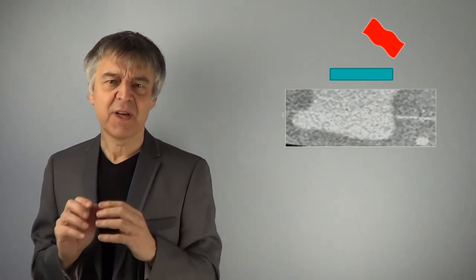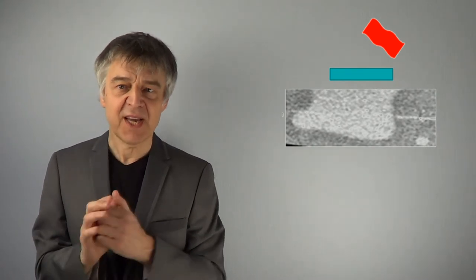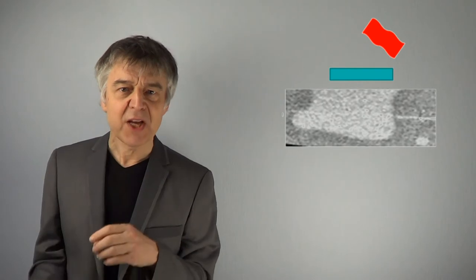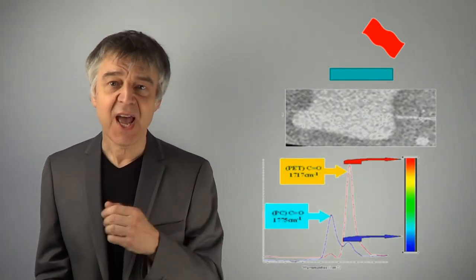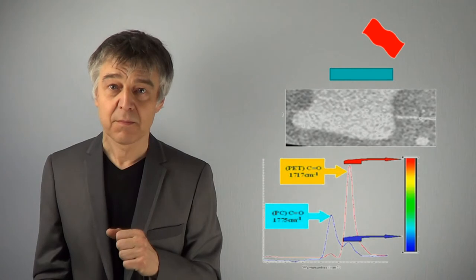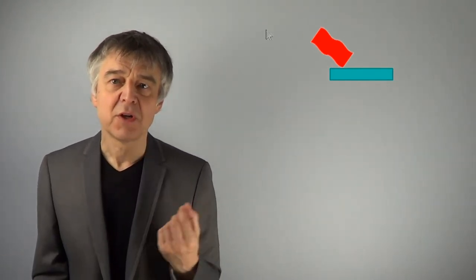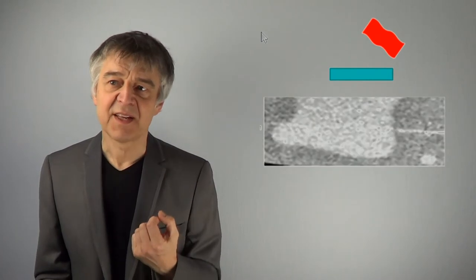By means of infrared spectroscopy in ATR mode, we can distinguish the vibration bands of PC and PET clearly. And we may now visualize the polymer distribution from infrared scanning data.